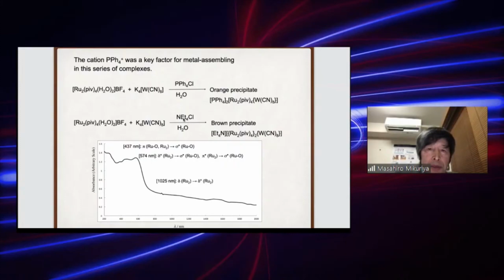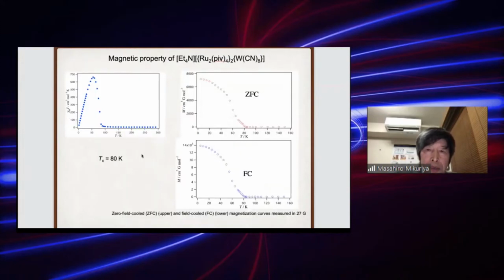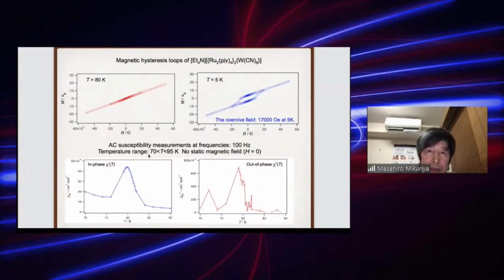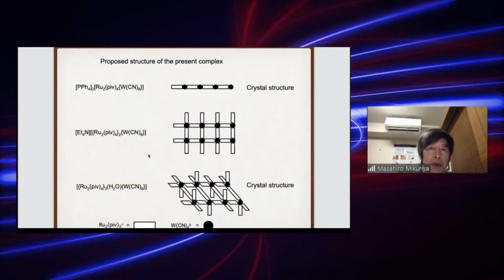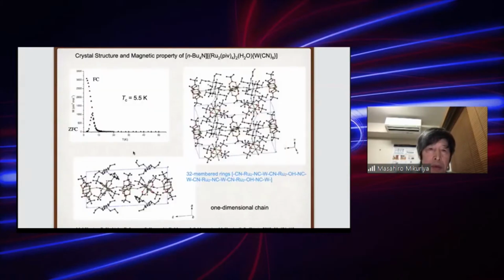Yeah. Almost ending. We used the tetraethylammonium chloride in place of this one and obtained similar paramagnetic compound like this. Tetraethyl. So we sweep this compound to dimension 1 and for other tetrabutylammonium, we could obtain a single crystal, and we see chain compound and counter cation here. This one is loosely connected to ruthenium unit.